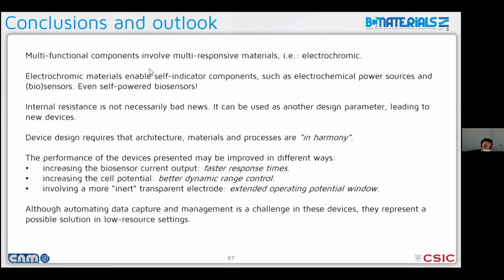So as a summary of the conclusions, if you want to have multifunctional components in a device, you need to involve multi-responsive materials. In this case, electrochromic materials are redox materials with a color change as a function of oxidation potential. These electrochromic materials are very nice because they allow you to build self-indicator components. So you can have self-indicator batteries or self-indicator sensors, as in this case. Internal resistance may be a bad thing in traditional electroanalytical chemistry, but in this case, you can actually use it to make a nice working device.